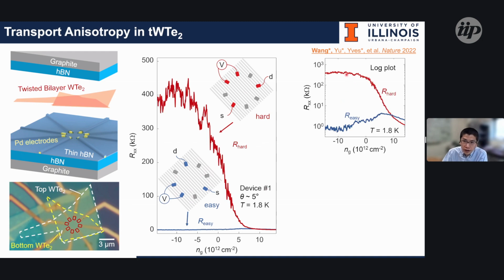If you check them in the log plot, you can see that along the so-called easy direction, where the one-dimensional system parallels the transport direction, the resistivity or resistance is on the scale of 1 kilo ohm. Along the hard direction, which you need to transfer across the wire, you get resistance on the scale of a few hundred kilo ohms.